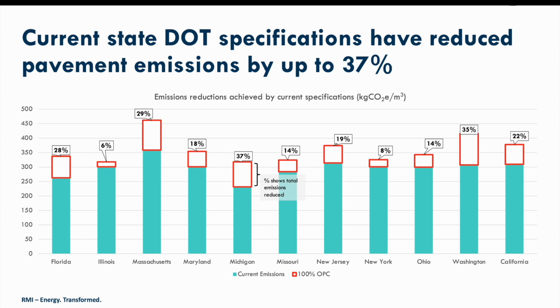Michigan has the biggest reduction potential due to their specification allowing for the implementation of up to 40% fly ash as a supplemental cementitious material. In the case of our earlier example of Florida and New York, we can see that Florida has a lower potential specification emission of 263 kilograms of carbon dioxide equivalent per cubic meter of concrete compared to 301 for New York. Both have the same minimum required strength, but Florida has a lower minimum required cement content.